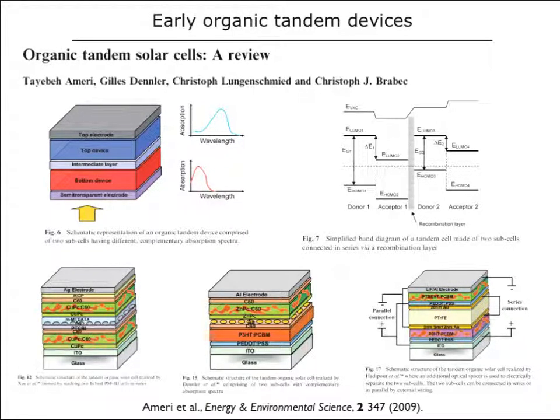And there's really a myriad of ways to fabricate these. What's really critical is, one of the critical components is the interconnect. Just like in inorganic tandems, that's a problem for us, at least in fully understanding it. And there's a number of ways to get around that. One of the ways is to use metallic nanoparticles as recombination sites in the interconnect layer. Or we could use a combination of some oxide materials and conducting polymers to act as efficient recombination layers.